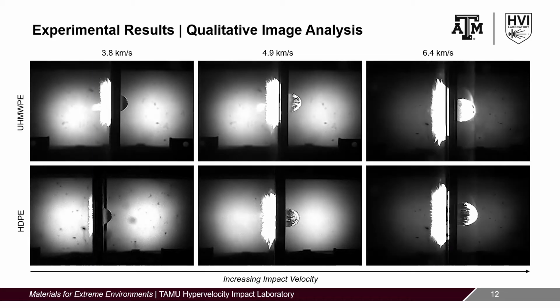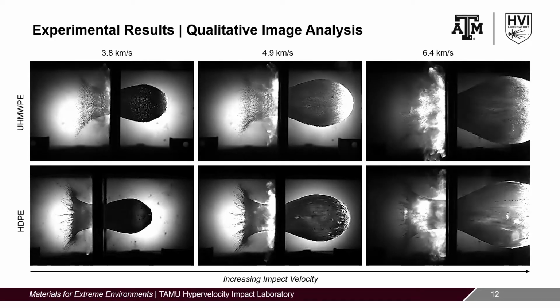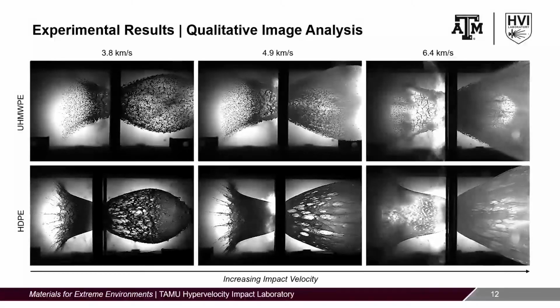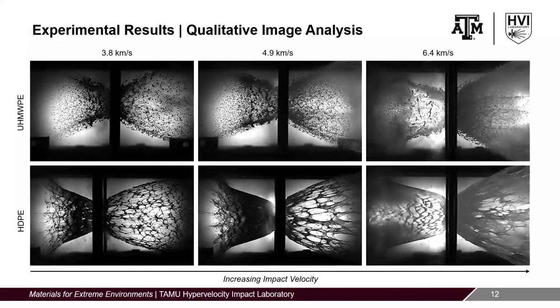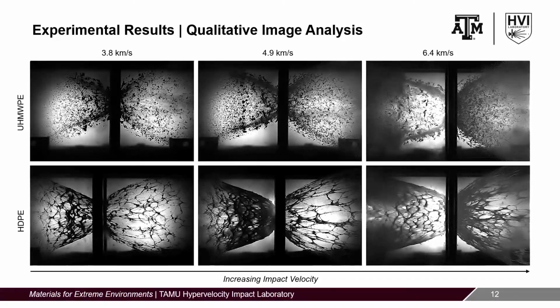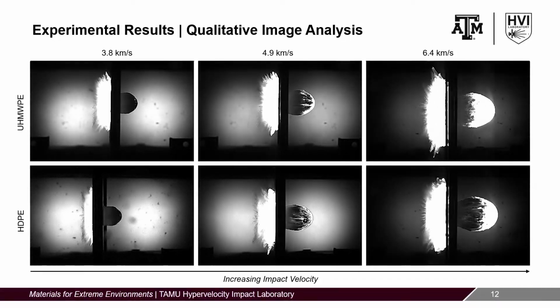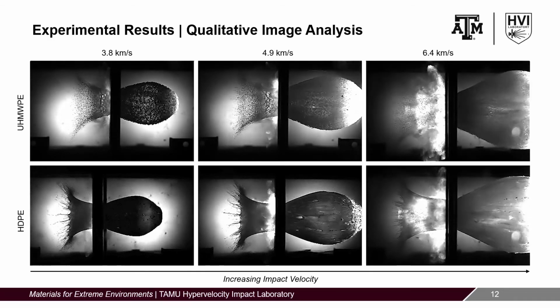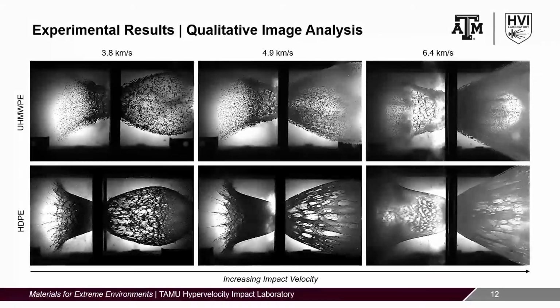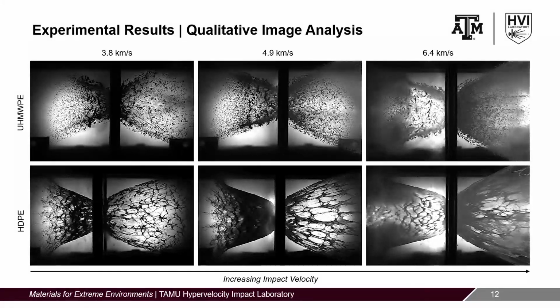A total of 27 hypervelocity impact experiments were conducted and analyzed. For these tests, 10 mm 1050 aluminum spherical projectiles were accelerated to velocities ranging from 2 to 7 km per second. The impacted specimens were 30.5 by 30.5 centimeter square plates, all with nominal thicknesses of 6.35 mm.